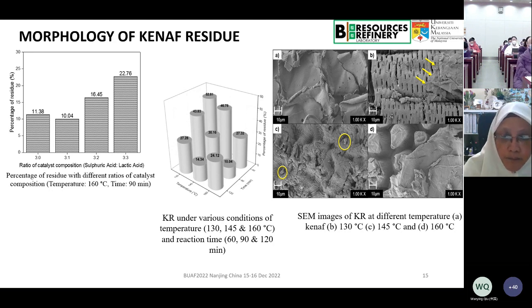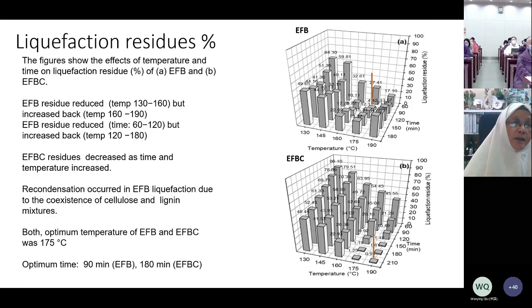The most important part is to make the residue as low as ever, because you will notice that some of the residue is very high, because unlike oil palm empty fruit bunch, Kenaf is very hydrophilic. If you add solvent in the system, it tends to absorb so much solvent that the solvent becomes less reactive as a liquefaction reagent. So you have to modify the process when you are doing Kenaf in this liquefaction process. For oil palm empty fruit bunch it is much easier.